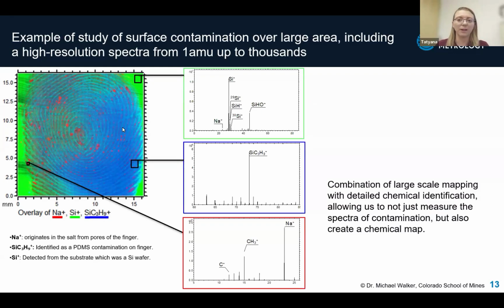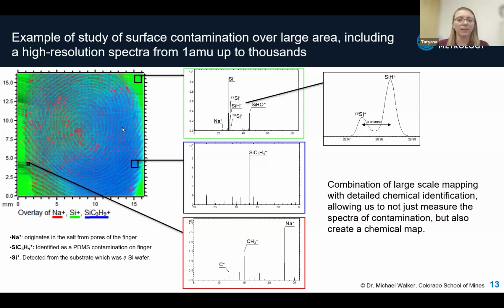The spectra on the right are extracted from the measurement during post-analysis. The area of analysis may be as small as a few square microns. We can see the incredible molecular details this technique provides. The top green bordered spectrum shows various silicon peaks, including isotopes. Zooming in on 29 atomic mass units, the region demonstrates the impressive mass resolution. Peaks are separated by 0.01 atomic mass unit.